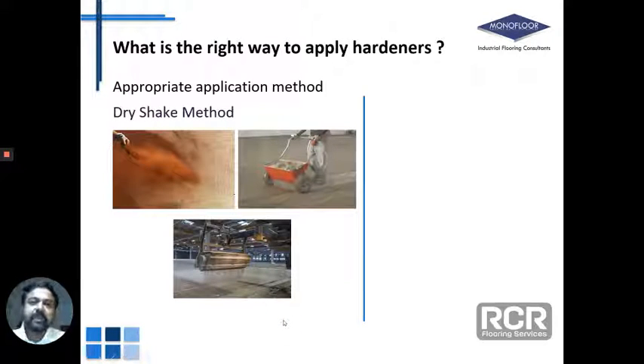The best way, if you're using hardener in a dry shake method, is of course to use mechanical hardeners, fully automated mechanical hardener spreaders. These equipments are prohibitively expensive. They're not available in India yet. But if you are using these equipments to dispense your hardener, you can dose really good amounts of hardeners, say even up to a thickness of 3-4 millimeters, which is about 7-8 kilos of hardener.